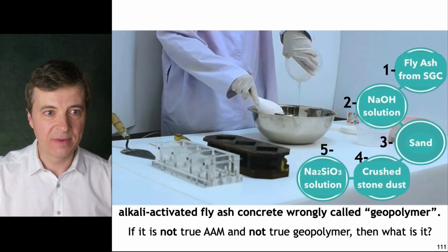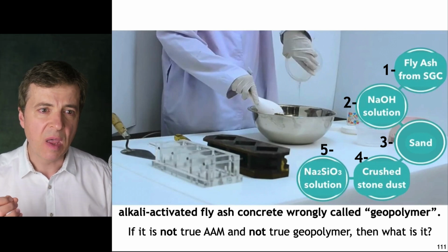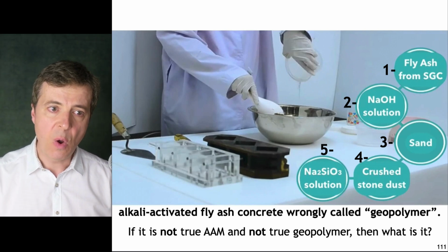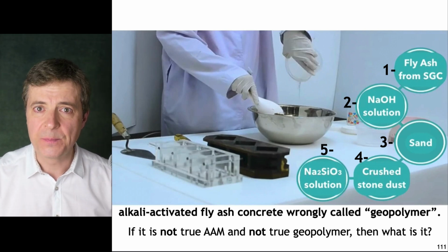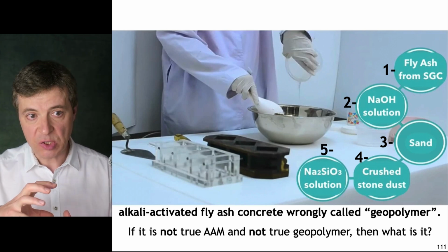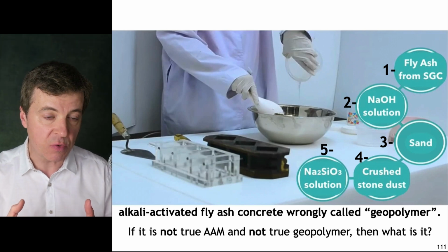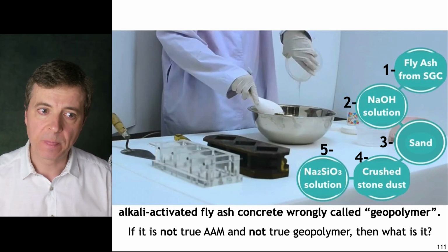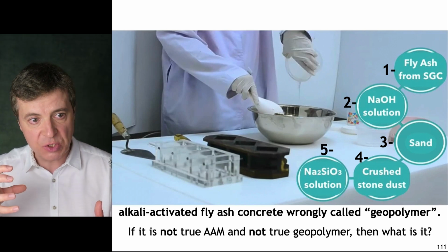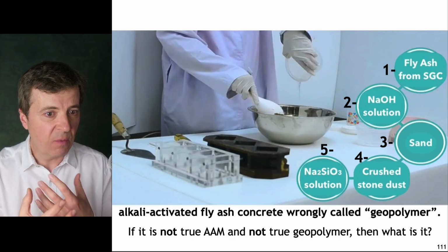Problem number 1. They don't give enough time, only a few minutes, for the NaOH to dissolve the fly ash, when it takes hours. Instead of attacking and dissolving fly ash, some NaOH covers the surface of the sand and crushed stones for no reason. As a result, some NaOH is removed from the fly ash dissolution, so there is less NaOH to react with fly ash.